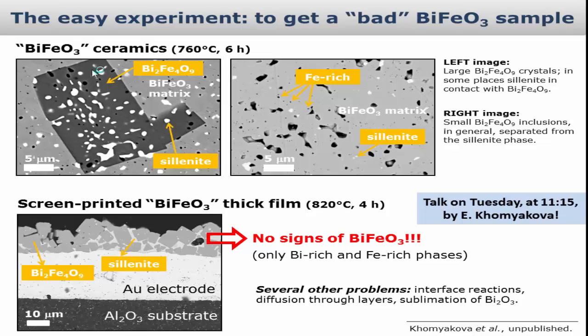Sometimes it is good to look at these secondary phases and how they appear, because they appear differently in different forms, and you can get some clues as to why they are formed. For example, these are two batches of BiFeO3 prepared in a very similar way. In one case, we saw these huge Bi2Fe4O9 crystals in which you have the sillenite phase embedded inside, and you can see there are contacts between secondary phases. It looks like they don't want to react further. They're stabilized there, and that can be explained, as I will show you later, by phase diagrams. In other cases, you have small inclusions of the iron-rich phase and the bismuth-rich phase, which are somehow separated, and this can also be related to reaction kinetics, which I will talk about later.